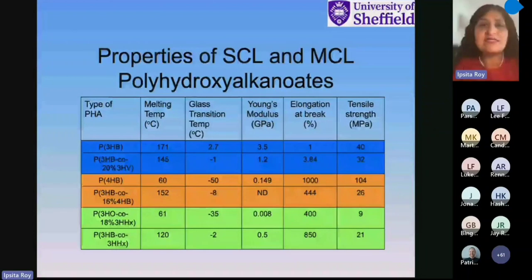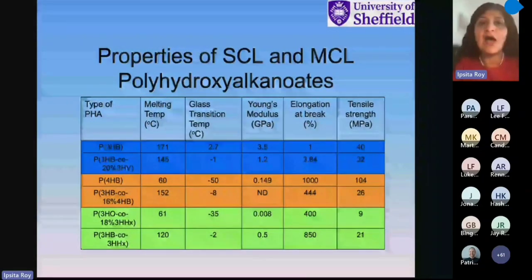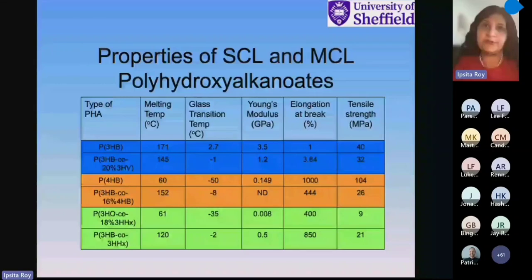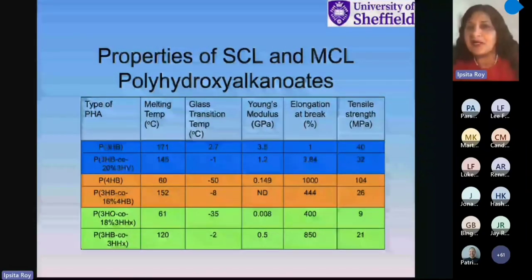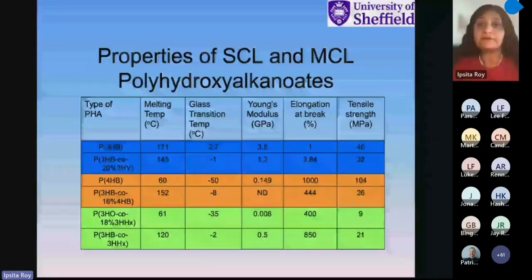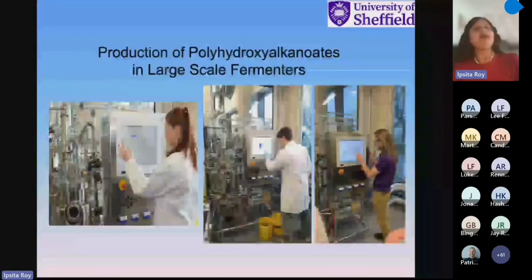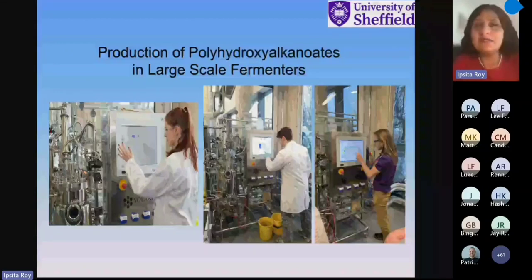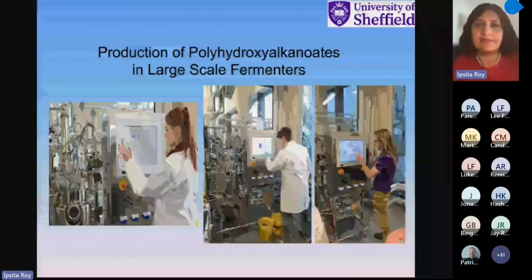And this is just a table. I'm not going to read it all out to you, but you can see the variety of properties in these polymers. Young's modulus going from a value of 0.008 gigapascal to about 3.5, elongation at break going from 1 to about 1,000. So I'm sure that gives you an idea. So this is the pilot plant in Sheffield where we produce these polymers using bacterial fermentation.